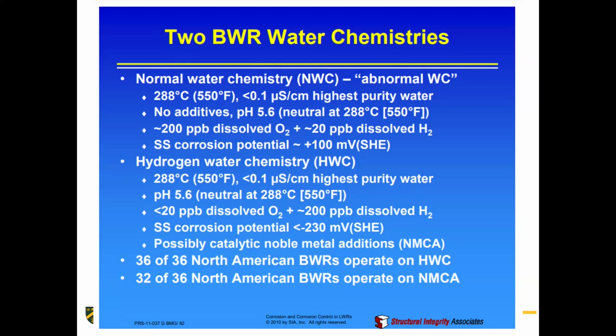So this has come up before. I've been showing you those diagrams looking at the fundamental thermodynamics of these things. If you pump a whole bunch of hydrogen into the system, you will lower your electrochemical potential. You will drop it overall if you end up sparging your water with hydrogen. And so that's what they did, and it ended up working quite well when it came to preventing corrosion. So dropping oxygen incredibly low, much lower than what it was under normal water chemistry times. And then overall, the stainless steel corrosion potential ended up being below the threshold for kicking off this SCC.